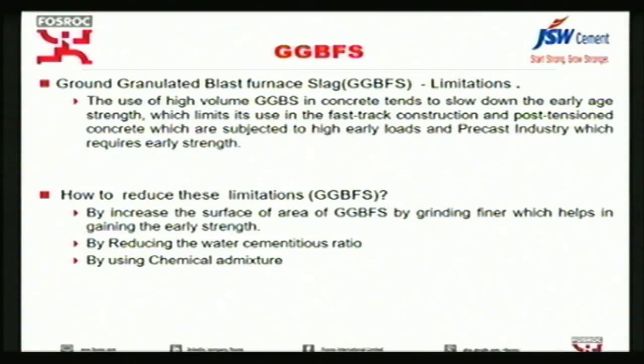We have many advantages with the GGBFS. The one limitation I can say, to overcome this limitation, probably we can increase the surface area of the GGBFS so that the hydration reaction will be slightly faster. What we understood from JSW is that earlier they used to have around 320 surface area. Now they are grinding it to 380. That could be one of the reasons it can help in getting the early strength.